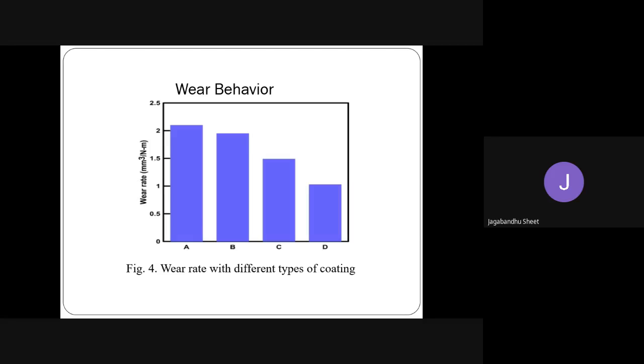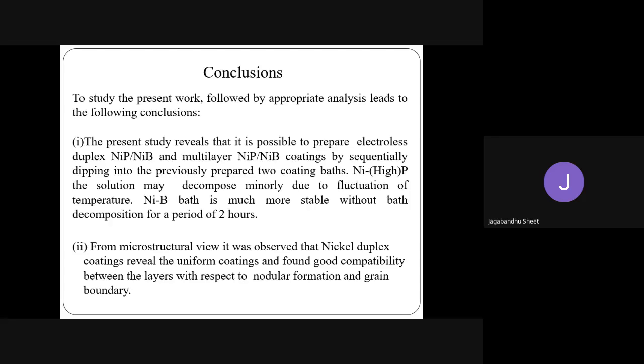Also, toward the multi-layer coatings, we have a comparison between C and D. We can see that with NiP as the outer layer, the wear rate is high, and with NiB as the outer layer, the wear rate is very low. And these are a few conclusions about that.